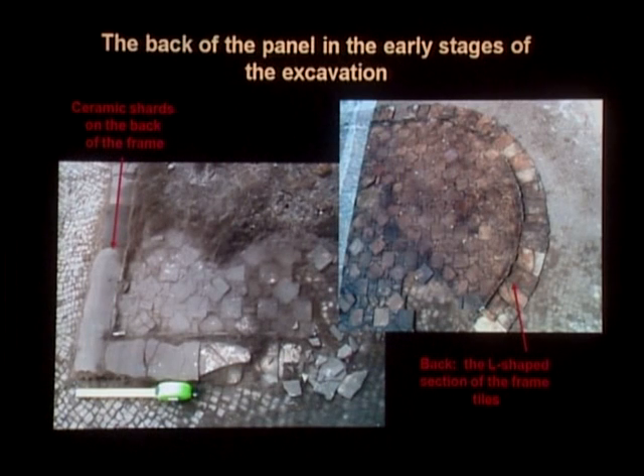The tiles of the frame are characterized by a rectangular shape and an L-shaped section. Above the frame tile was found a layer of broken ceramic vases, which protected the frame from the fire and collapse of the building. The back of the panel, which was probably made of organic material, was totally burnt. We still don't know if the panel was attached to a wooden board or frame or glued to a mat. No remains of plaster or any kind of paste were detected.